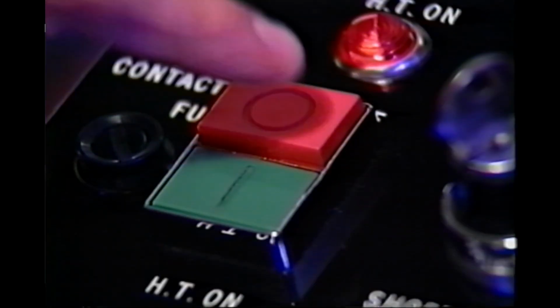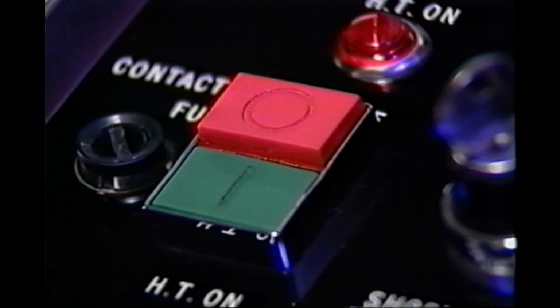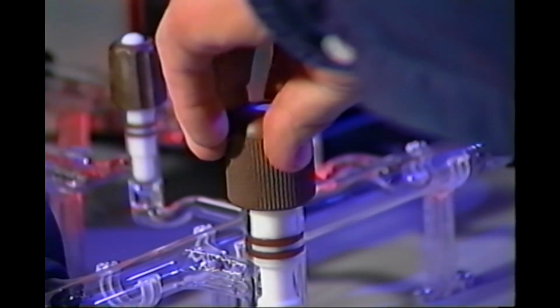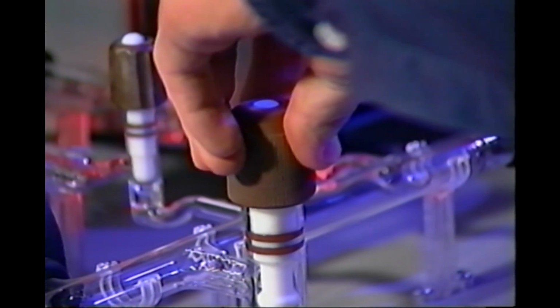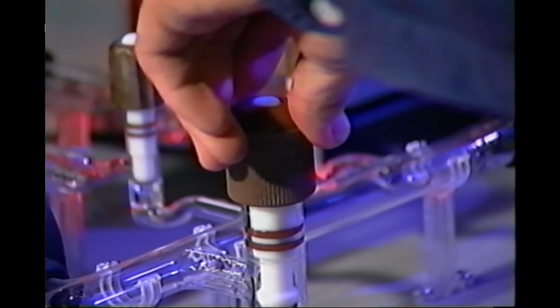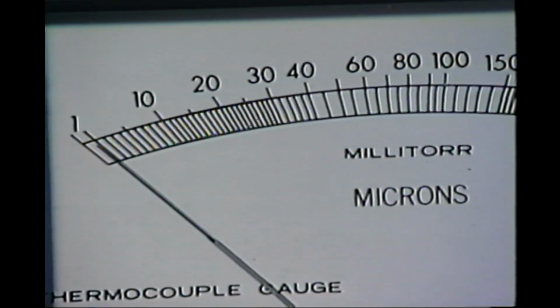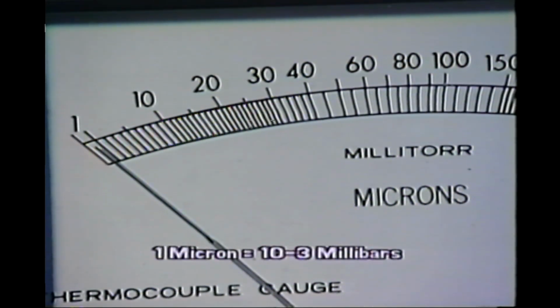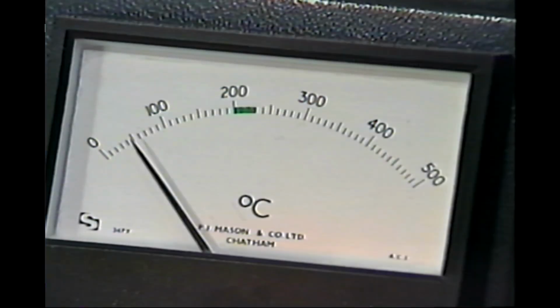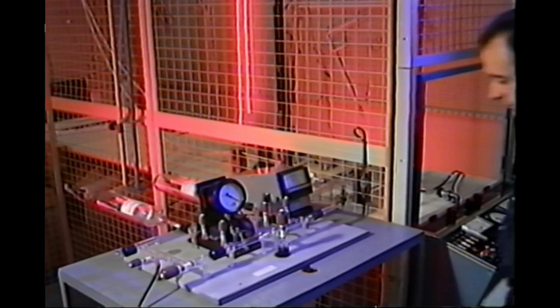At the end of the 1 minute running time, if the gas color is satisfactory, switch off the current. Open fully the main stopcock and allow the tubes to cool and evacuate. Once the tubes have fully evacuated to 1 micron or below, and the tube temperature has fallen below 50 degrees centigrade, the final stage of processing the rare gas filling can take place.